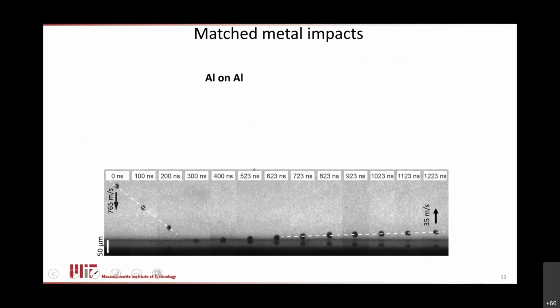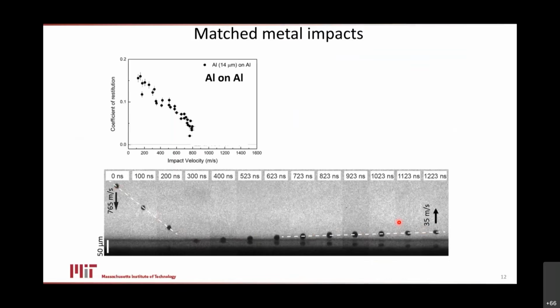So this collaboration led us to do a lot of work on what I call matched metal pairs. So you're shooting a metal at itself, basically. Now I'm launching aluminum particles, they are impacting aluminum substrates, and I'm measuring the mechanical response of like on like during one of these impacts. Again, we would do a high throughput kind of study where we'd shoot a few dozen shots that are nominally identical. The only exception is that we do this at different velocities. So now we get a response curve. Here we're measuring the bounce, and again, we're getting less and less bounce as we go faster, and that is a signature of plasticity. I'll show you in a few moments that we can use this as a way to measure plastic properties.